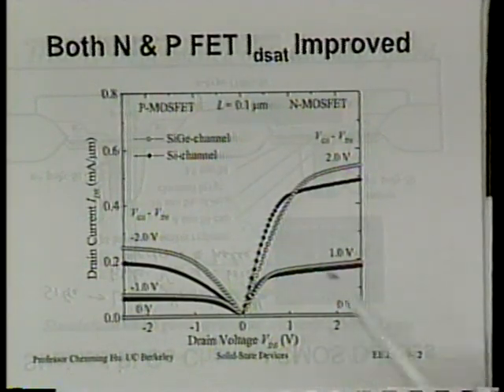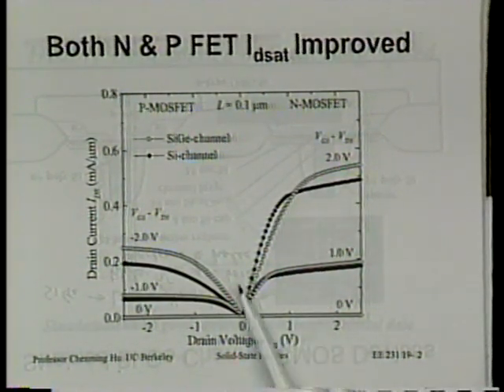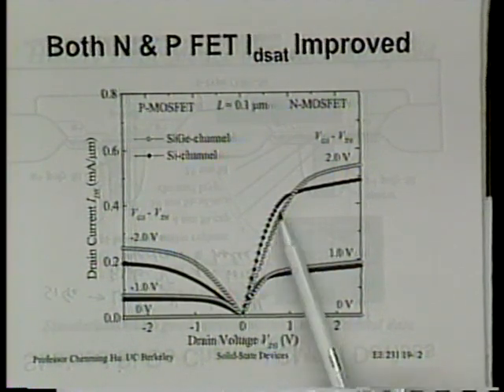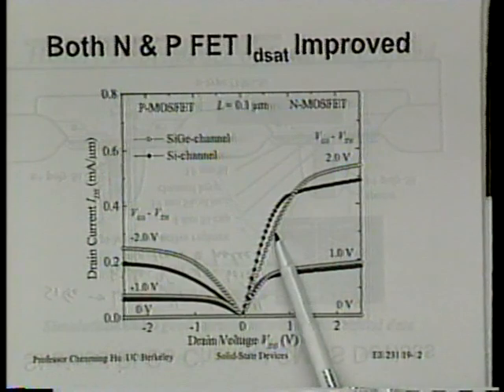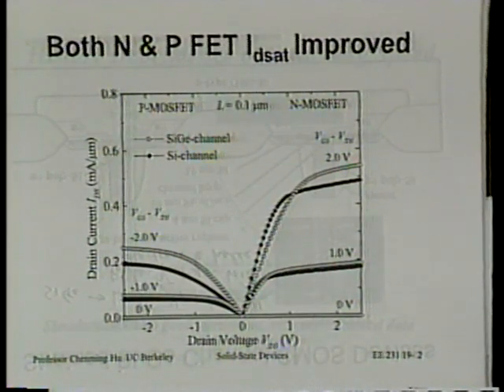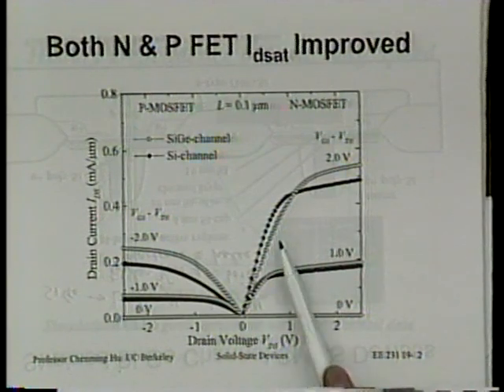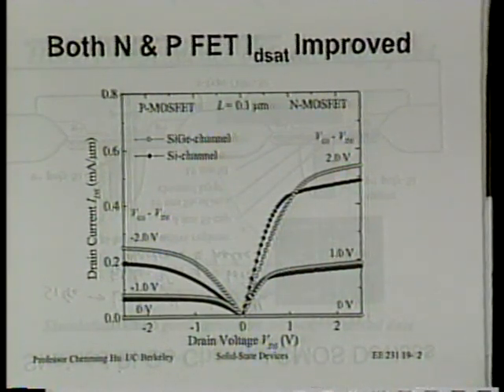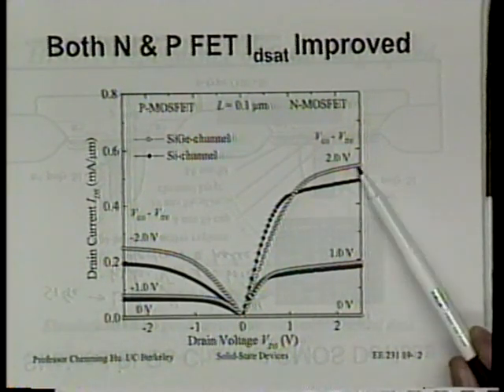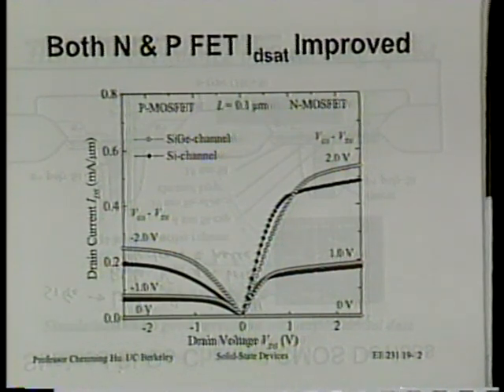On the N-channel side, you notice when the VDS is low, silicon germanium yields lower current than silicon. This is the well-known problem: the electron mobility is actually lower in silicon germanium. You see that? And yet, when you go to saturation current, it becomes a larger current. Now, this was not noticed before because people used to do all this experiment in long-channel transistors. And this was done 10 years ago, so it has been examined and then abandoned. So this just illustrates that indeed the saturation velocity is better.